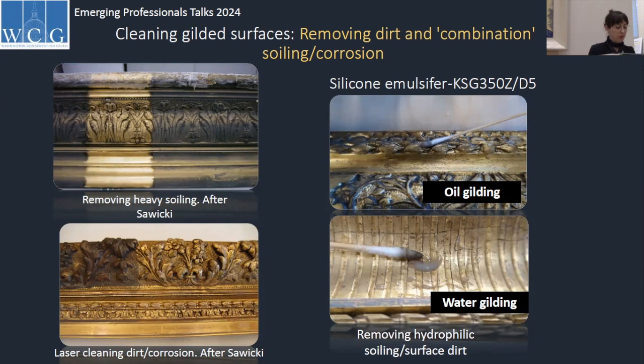Water gilding is particularly sensitive to polar organic solvents and also to water-based solutions, and this forms a large part of what we have available to us with a lot of gel technologies. So the efficacy to remove a lot of the surface soiling is reliant on water-based systems, which the gilding is very sensitive to. I've just got up here some images where you can see just how filthy and soiled frames get and how we do want to remove that.